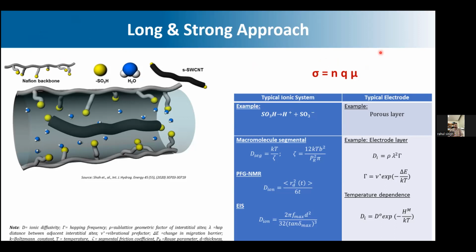As we have seen, increasing the ion exchange capacity can make our system fragile, so that one needs to be taken into consideration. Here are some formulas I have mentioned. If we want to understand how the number of charge carriers and mobility play a dominant role, we need to calculate the diffusion coefficient, or diffusion value, inside this membrane or polymer electrolyte.